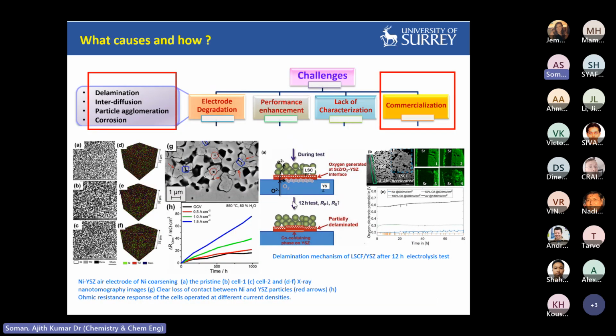And so what are the real causes, or what makes the cell get degraded? It is again, as I told you, our colleague Victoria also explained. It's a kind of interdiffusion effect and particle agglomeration, and of course a lot of corrosion issues. So our technique, like the silver coatings, will address the corrosion effect, because silver is less corrosive and is a noble metal, so it can effectively increase the current collection, so we can tackle this corrosion effect.